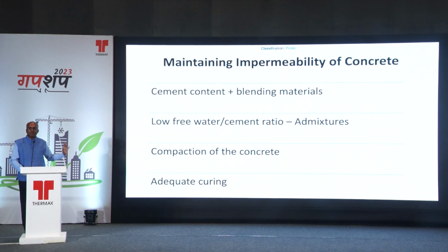Of course, these are the basic things that we need to keep in mind. How do we maintain impermeability in concrete structures? We can take RMC, which has a controlled way of making concrete. Precast has a controlled way of making. But what about site mixed concrete? In site mixed concrete, we need to see how we can maintain that. In many of the places where we go, we see that the water cement ratio is not controlled. But today technology has come where the water cement ratio can be reduced to as low as 0.2 or 0.25 by the use of chemical admixtures.